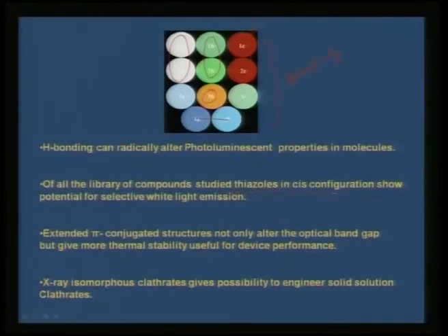And of all the library of compounds studied, thiazoles in cis configuration show selective white light emission. Extended pi conjugated structures not only alter the band gap, but they give more thermal stability useful for device performance. And lastly, I have shown you an example where X-ray isomorphous clathrates can help us engineer solid solution clathrates to get a compromise between PL emission and mobility of the charge carriers.